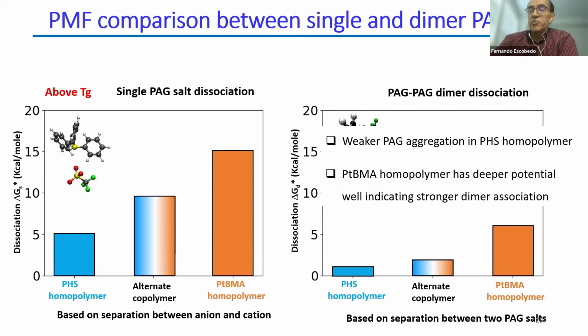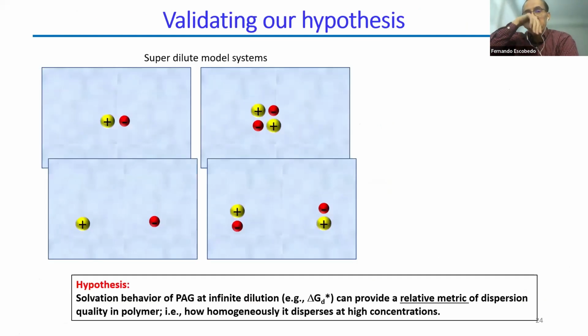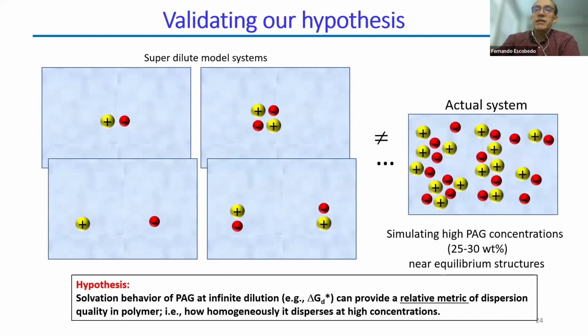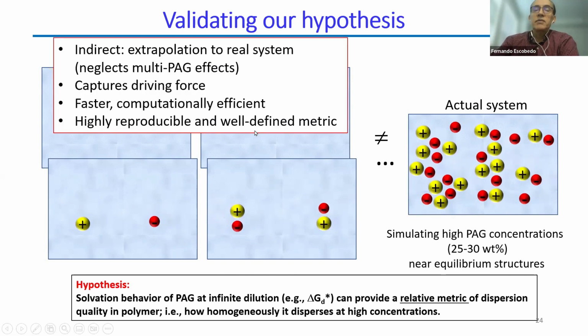So these were good predictions, but we wanted to confirm them. To confirm them, what that means really is that we also want to simulate the actual system, a system where you have these salt molecules at high concentrations, on the order of 25, 30, 35% in weight. Because really these two things are not the same. You may wonder, why don't we just simulate this actual system and forget about this dilute system? Well, there are many reasons.